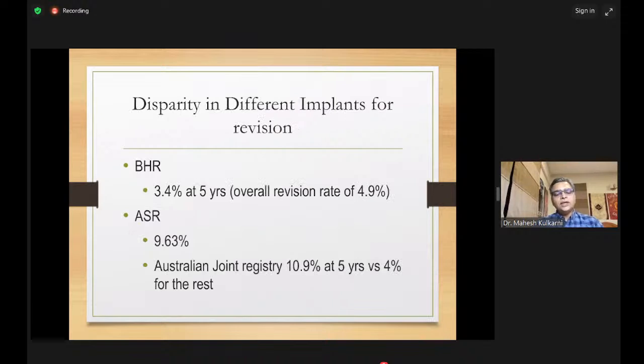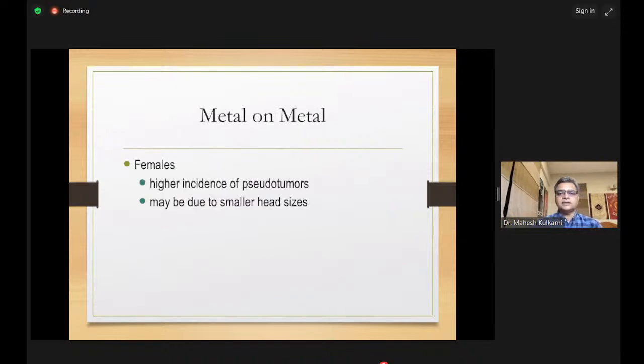Now, if you see two companies, one was the Birmingham hip replacement, which was really the top performing, had very less revision rate as compared to ASR, which was like a shock wave which was sent through the orthopedic arthroplasty community around 2008-9 when the failure of ASR was brought out and all the metal on metal implants were pulled out from the market, apart from the BHR, which continued to function with excellent results.